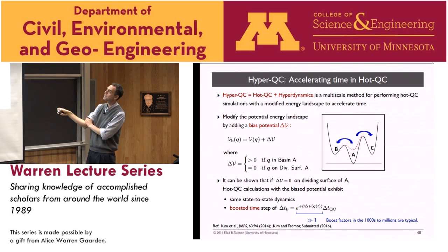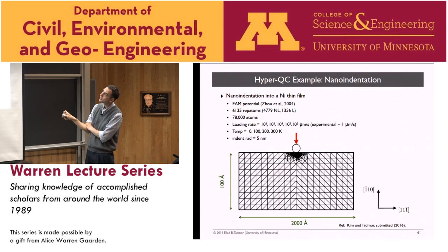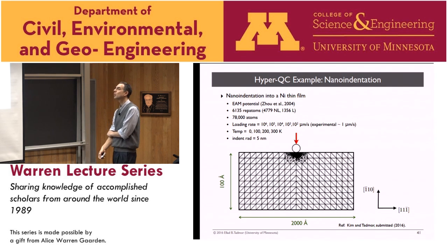And so we were able to rerun the simulation that I showed you before for this case, and you see the main point is right here, that we can bring the loading rate down to 10 to the 2 from 10 to the 6. And in fact, I think we're going to be able to reach further down than that. So we're already much, much closer to the experimental rates. And still working on this, but that's where we are with that.